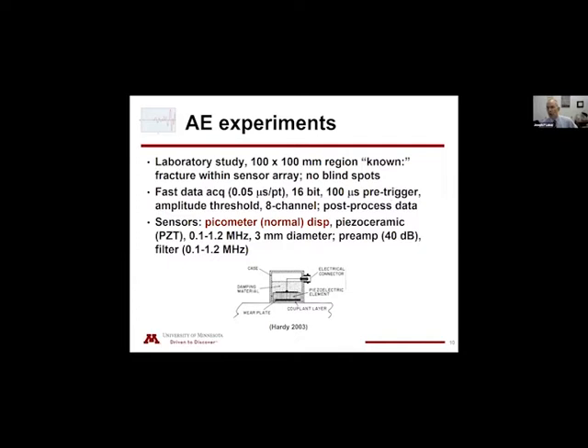So this so-called pre-trigger region is very important to us in finding the first arrival of the time history. For our location process, the first arrival of the signal, that is the arrival of the P wave, is what drives the location process. I mentioned that there are 4 unknowns in this location problem. Because of the quadratic nature of the distance equation, we should be working with 5 pieces of information, for example, 5 channels of signals. For us, we use 8.